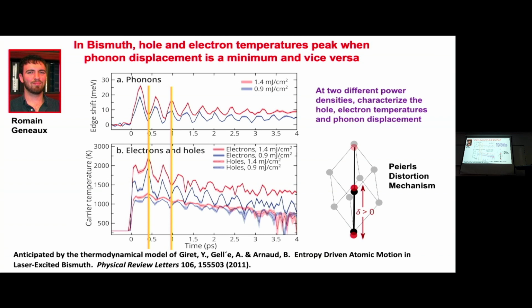And you might think, oh, now we've discovered the hugest new thing, but it turns out if you turn back the clock, there was a theoretical paper already in Physical Review Letters in 2011 that exactly described that this phenomenon should happen. And it's just a thermodynamic effect: you only have a certain amount of energy and you can partition it either between phonon excursion or electron-hole temperature. So they're completely anti-correlated. And we did it at 2 different power densities and everything checked out, very precisely according to the description of this theoretical paper.